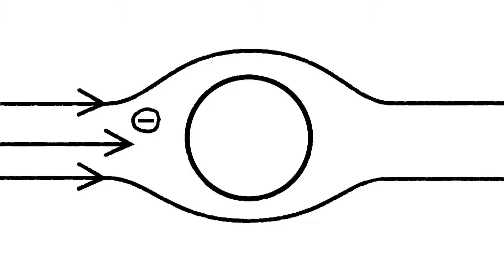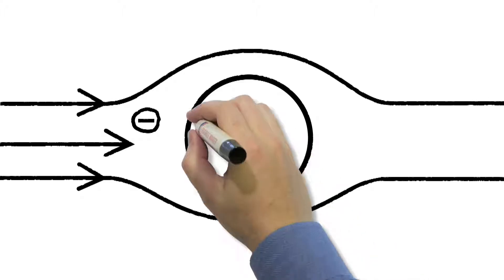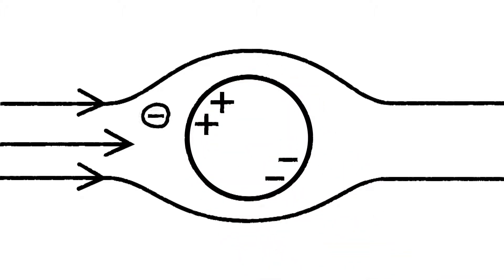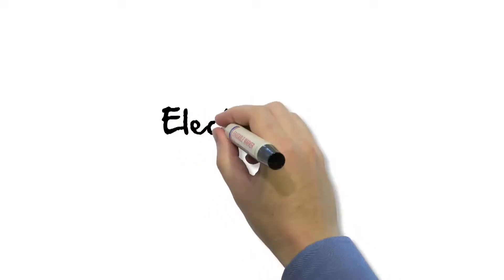We use a special polymer inside of our filters. It has a very special ability to polarize itself. So in the presence of a charged particle, it can show an opposite charge towards the particle, creating that attraction force. So it can be captured by the filter fiber, and we can increase the efficiency without increasing the number of fibers or adding any pressure drop to this process. And we call that force electrostatic capture.